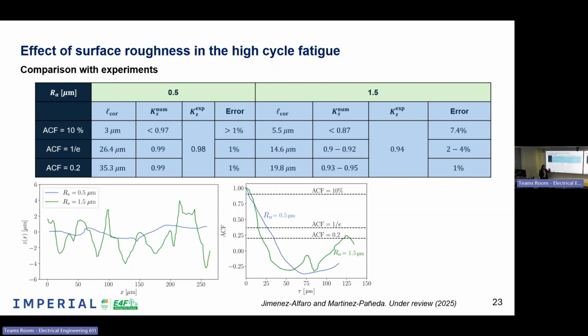So once we have the three different correlation lengths, because we have three different possibilities, we have computed our numerical result, our numerical surface factor, and we have compared it to the experimental one. As you can see, results are very accurate. In fact, the most accurate one is the ACF equal to 0.2, because the prediction has less than or around 1% error, so almost the same value.